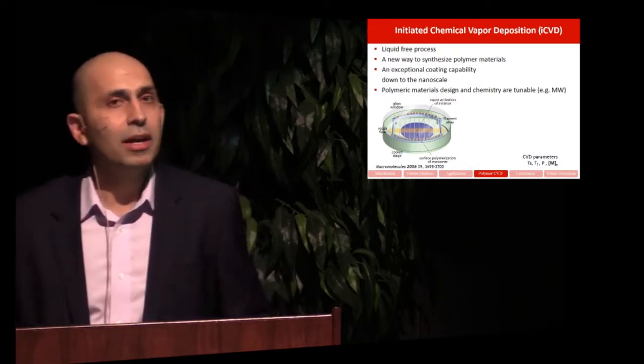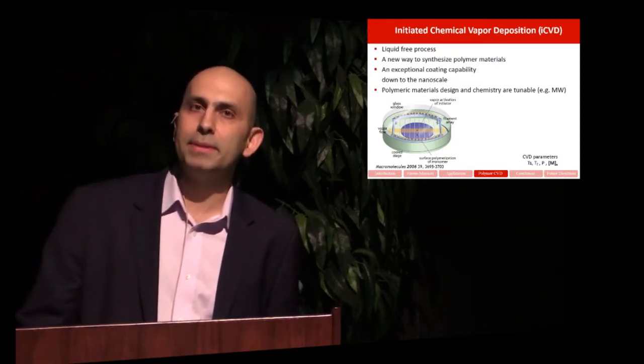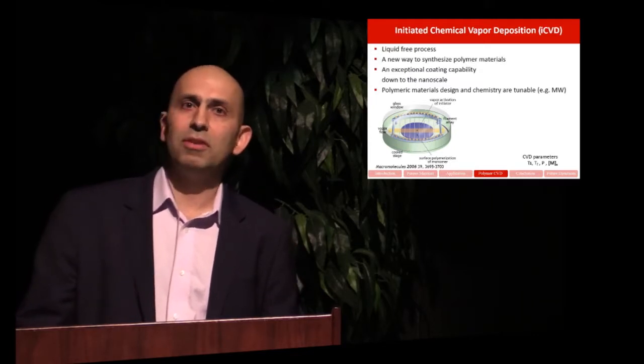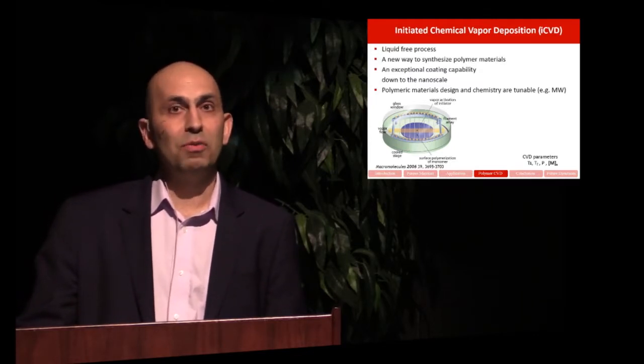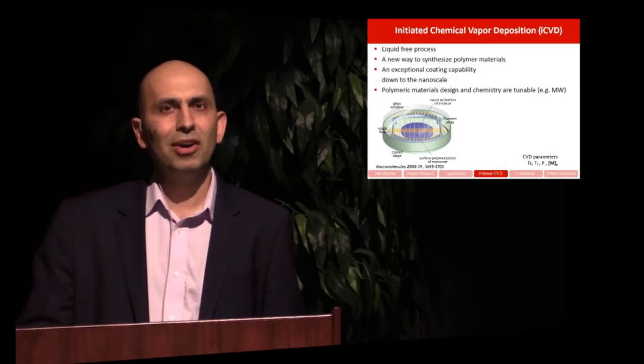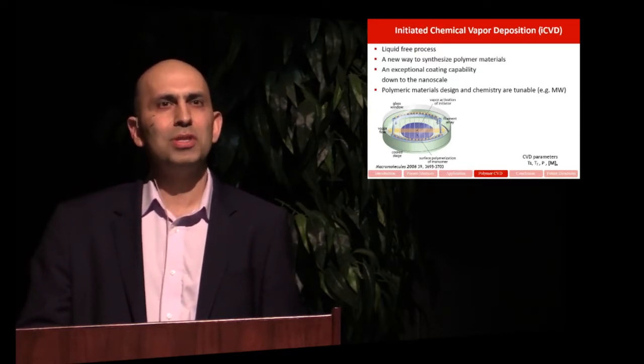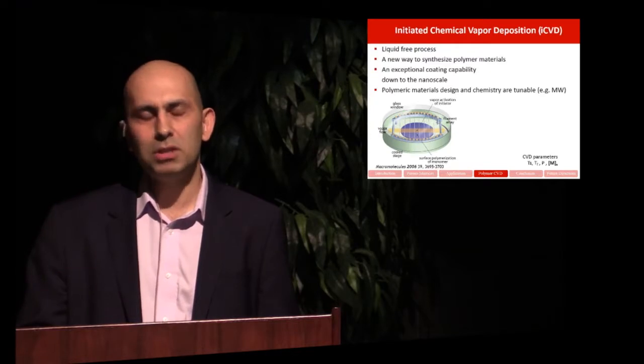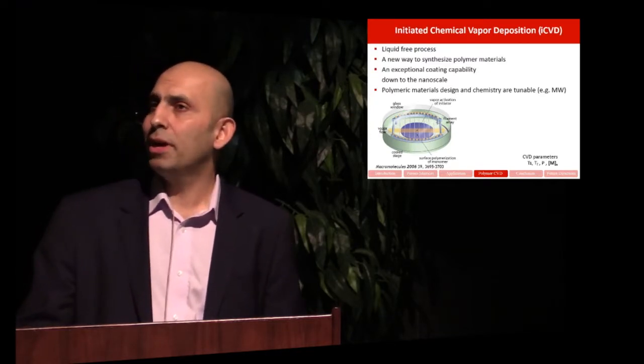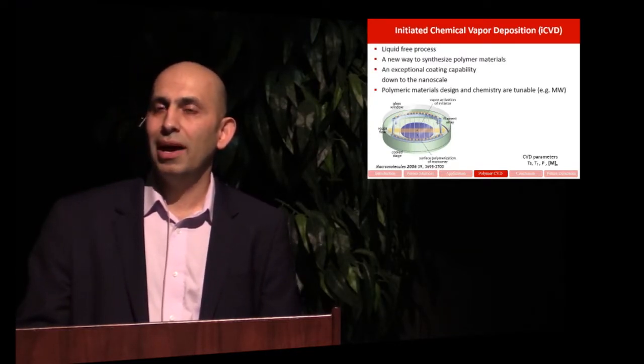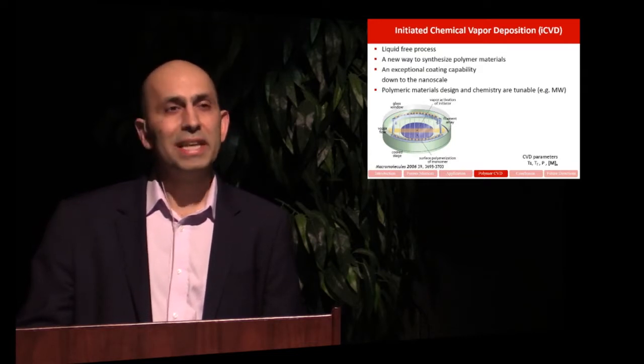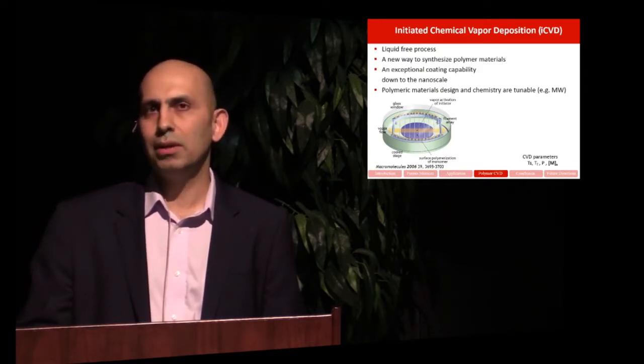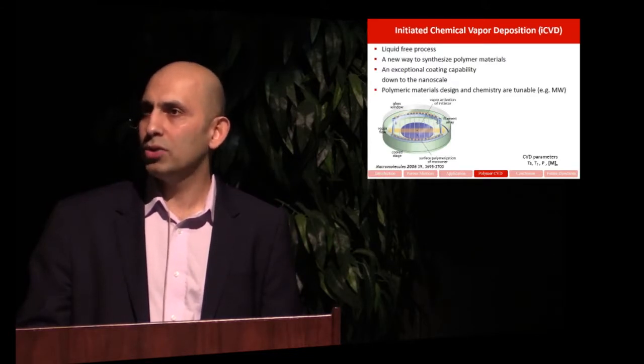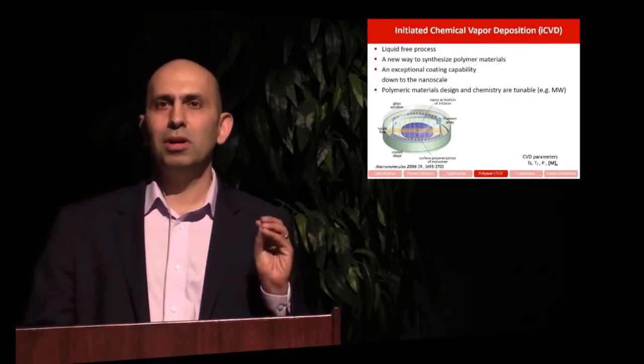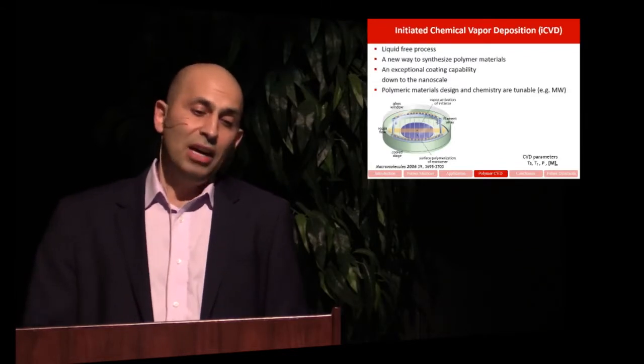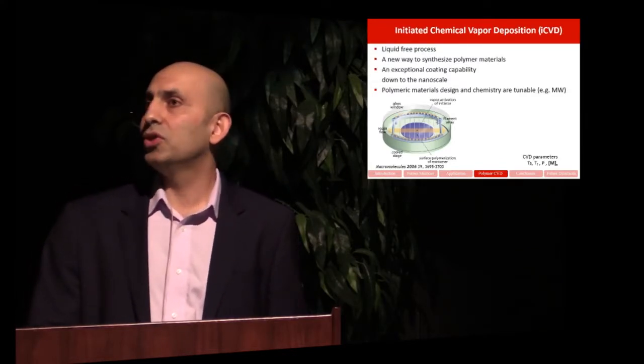So we came up with the idea of initiated chemical vapor deposition, and I've been working on the development of this process. This came from my advisor's lab like 10 years ago, and I have been working on that continuously to see what other possibilities we can have from this method. So it's a liquid-free process. There's no liquid involved. The way it works, we synthesize the polymer at the place we need it. If you want to apply a coating to something, you just coat the polymer where you need it. And we can control the properties of the polymer. That's the most interesting part about it.